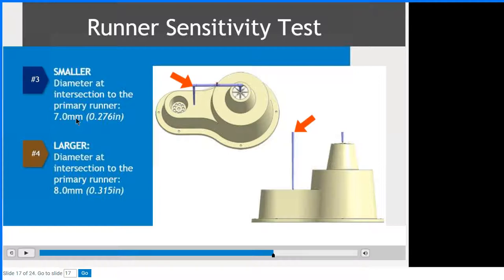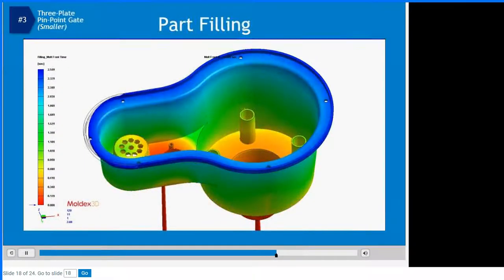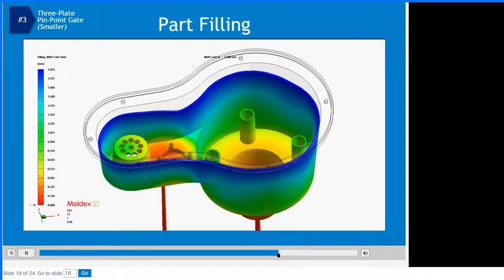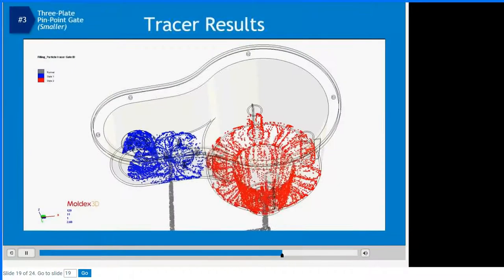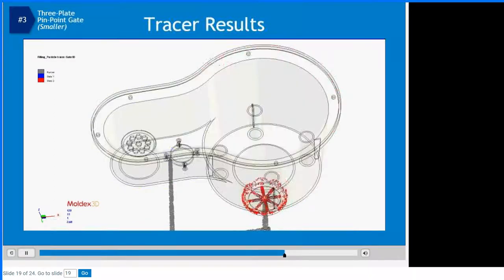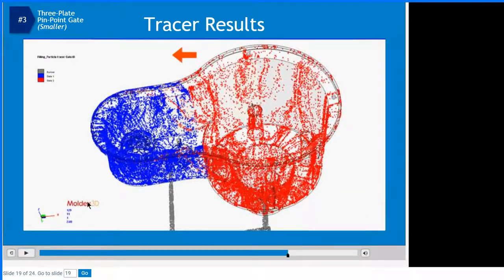On screen you can see a simplified three plate cold runner system along with the details for the two tests we will run. Because we are performing a runner design sensitivity test, notice that the difference in runner sizes between the two designs is minimal — only the cold drop leading to the smaller section has minor drop and gate size variations. The fill pattern analysis for the first cold runner design indicates the larger section is filled slightly before the smaller section. The tracer animation shows that at the end of fill, red tracers shift to the blue side, indicating a slight fill imbalance.